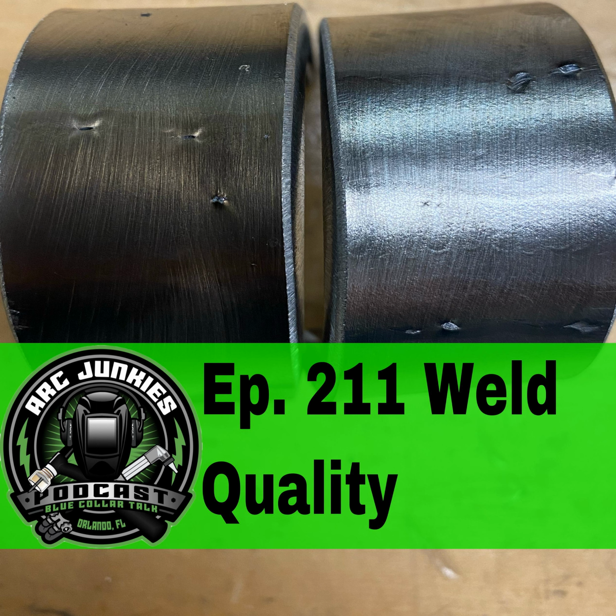Most of the time I see overlap, it's in a horizontal configuration, whether it's a horizontal fillet weld or a horizontal groove weld, where the weld is pouring over the edge because you're traveling too slow. So make sure you don't have any overlap whatsoever. If you're allowed to use a grinder and you have overlap, make sure you grind that down. You want a nice smooth transition between the toe of the weld and the base metal. You don't want that lump there. That's going to cause nothing but problems.